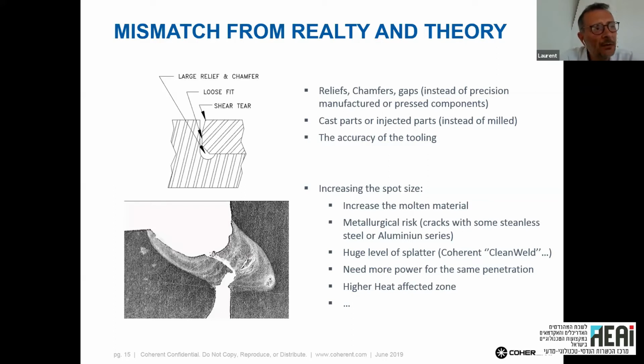You will increase the molten material. And if you have too much molten material, you can put also some oxidation inside. You can create some porosity. The heat affected zone will be higher because you will put too much energy inside the part. So the heat will increase around the weld. So in this case, we really need to adapt and to find a solution. And just by increasing the spot size, it will definitely not be enough.